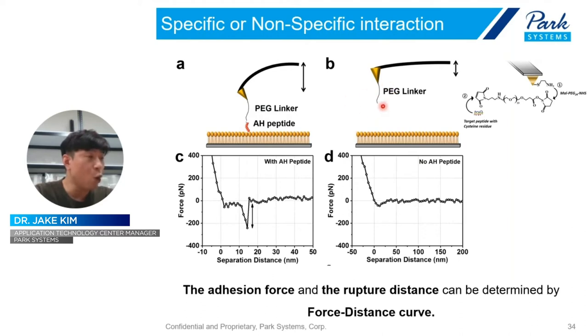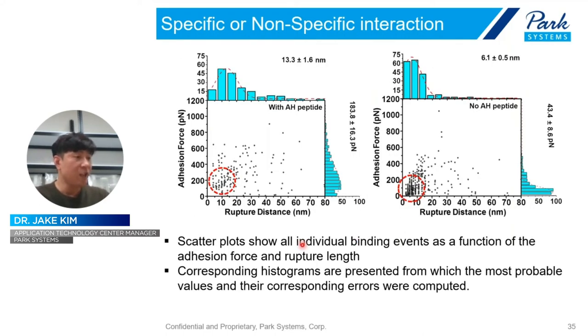But in the case of no AH-peptide, there is no interaction. So we can see the adhesion in one case and cannot see the adhesion in the other. And like this statistics, these scatter plots show all individual binding events as a function of adhesion force and rupture length. This is the peptide attached AFM tip, and it shows about 183.8 piconewton of force, but the no peptide case is just 43 piconewton of adhesion force.